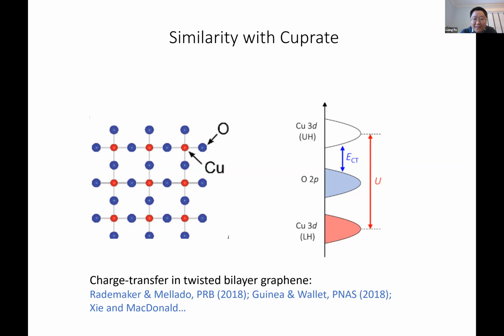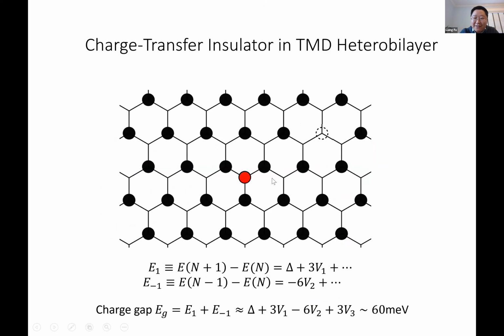So when we look at these TMDs, we plugged in the numbers. Let's see, next slide. Does this work? Okay, so when we look at the numbers here, one can ask the question, what is the charge gap in this charge transfer picture? This charge gap is defined as the energy cost of adding an electron plus the energy cost of removing an electron. The sum of the two defines the charge transfer gap, and the added electron goes into the cation site and the removed electron comes from the anion sites. So when we take both into account, the charge gap is about 60 millielectron volts.